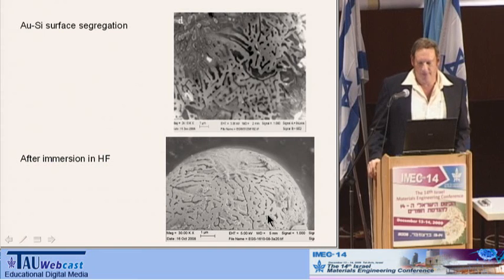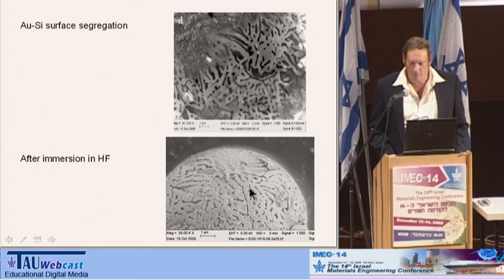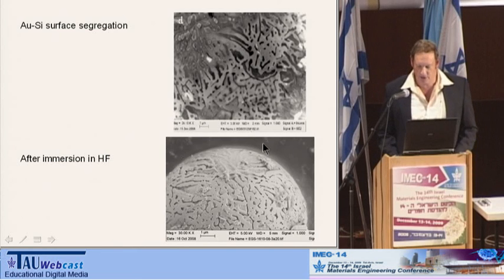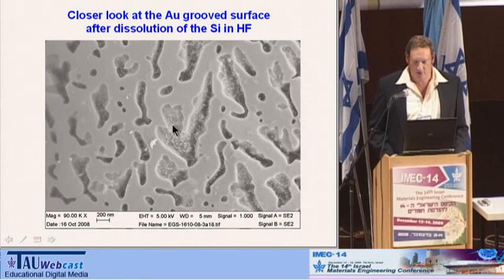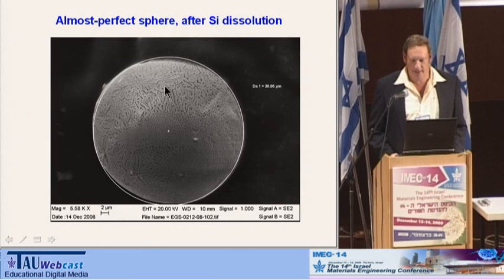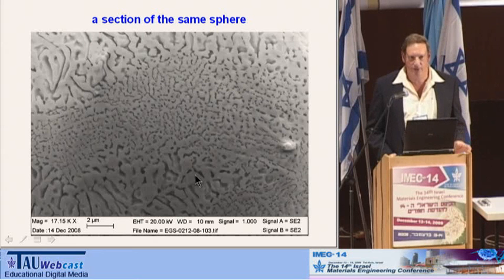Since we see phase segregation and the dark spots are mainly silicon, we thought that if we immerse these microspheres in hydrofluoric acid for a prolonged time, the silicon would be dissolved. Indeed, that's what we saw — after about a week, it showed a complete removal of the silicon, leaving a grooved surface with enormous surface area. A closer look at this surface shows cavities formed by etching or dissolution of the silicon. Some of them, with this scale bar of 200 nanometers, must be a few tens of nanometers. Another sphere treated with HF shows other structures — the diversity of surface structures that we see with gold-silicon is enormous.